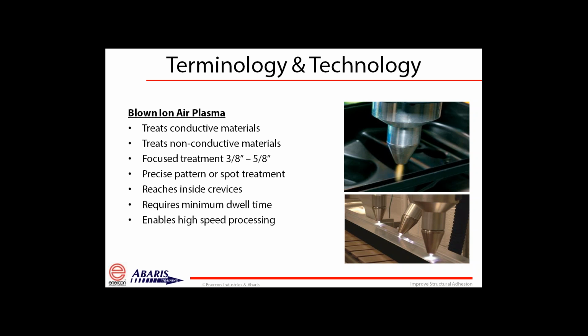That treatment is much more focused, typically somewhere in the neighborhood of about 1/2 inch wide. It does vary a little bit based on the speed and how close you are to the material itself. It's a very good technology for precise pattern or spot treatments. The picture that you see in the upper right is actually the back assembly component to a headlamp for your automobile. In this case, we're treating the glue track to enhance adhesion to make sure that that lens bonds and there's a watertight barrier in the headlamp.